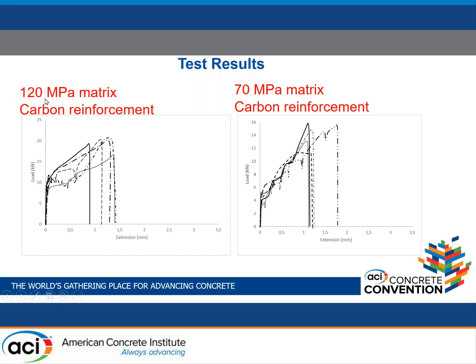One matrix is 120 megapascal compressive strength matrix, and the second is 70 megapascal compressive strength matrix. Although both composites showed similar extension values, the use of carbon fabric in UHPC matrix showed significantly higher load values.